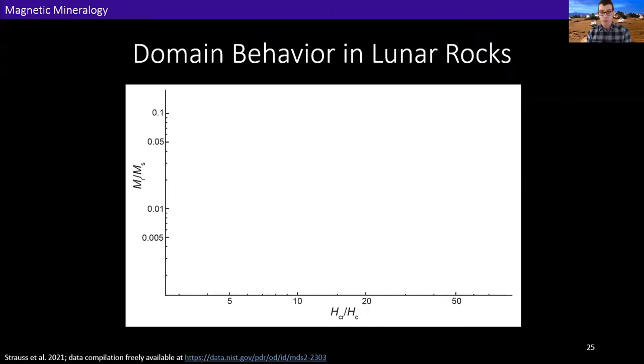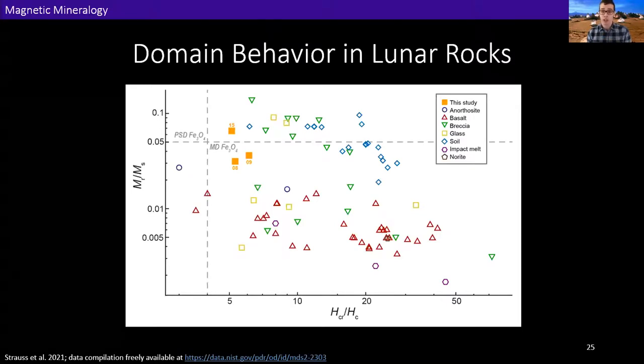So on our x-axis, we have remnant coercivity divided by coercive force. And on our y-axis, we've got saturation remnant magnetization divided by saturation magnetization. And the general hope with a day plot like this is that samples with better recording properties should plot toward the upper left and may correspond with better magnetic fidelity. So what we built in our study is, to our knowledge, the largest published compilation of hysteresis parameters from Apollo samples to date. Each data point that you're seeing here represents one sample or subsample from literature, sorted by bulk rock type, kind of as a first pass.